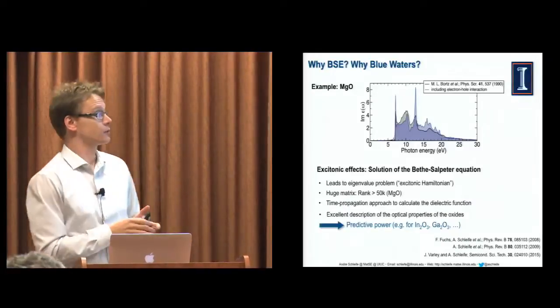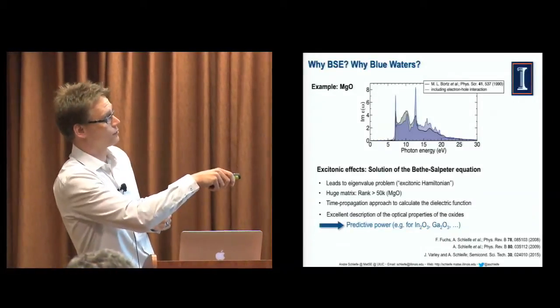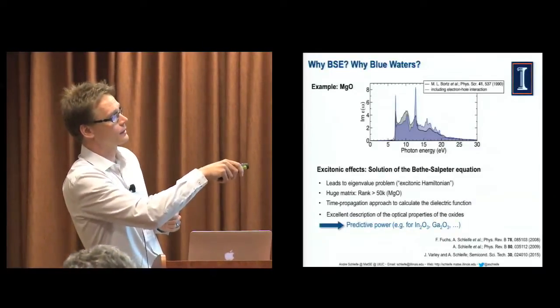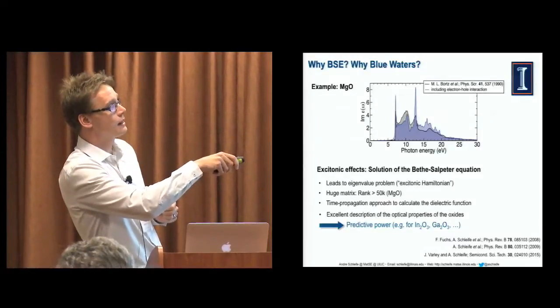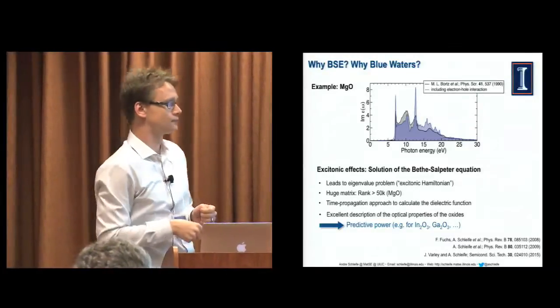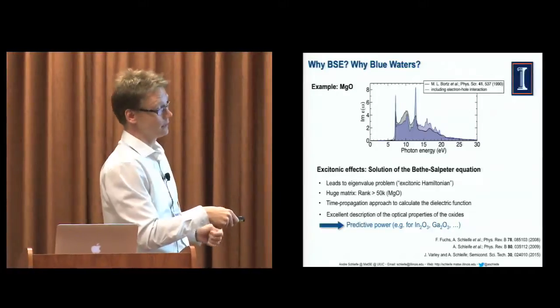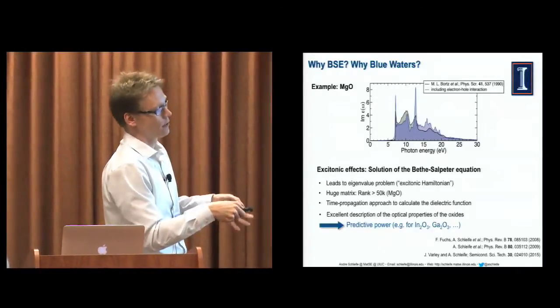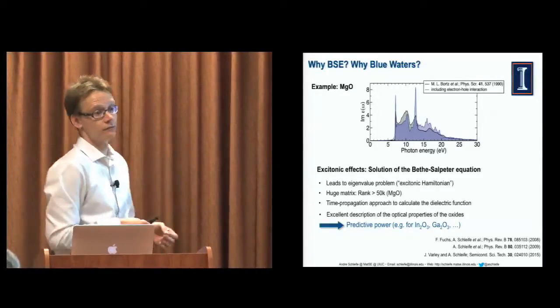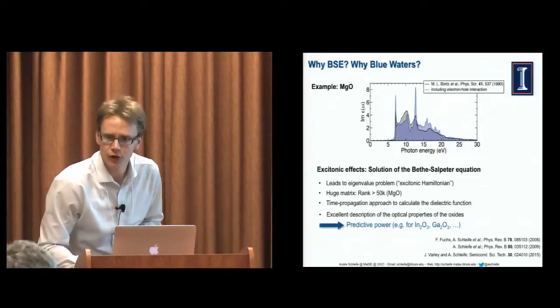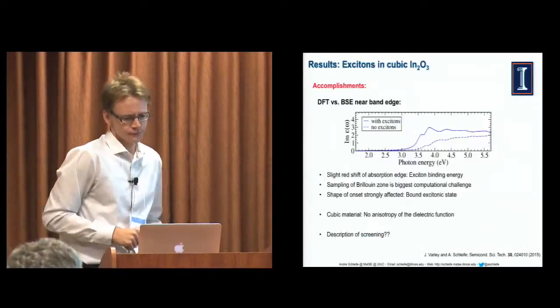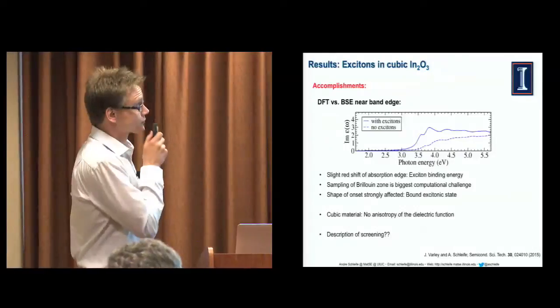And if you compare that to experiment, I guess that's what the last slide for this one shows you, we get very good agreement, right? We can describe the positions of peaks very well, sometimes even relative peak heights. So that makes us confident that we actually have predictive power, and we're going to apply that now to indium oxide and gallium oxide. Okay, so let me show you some results.